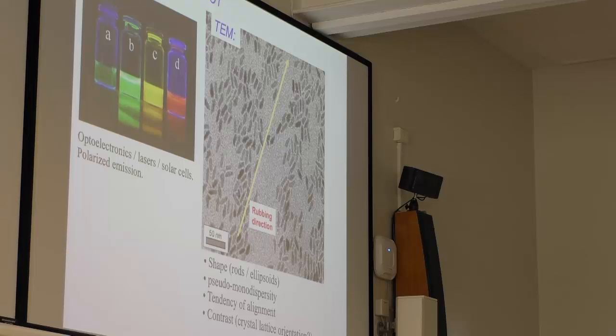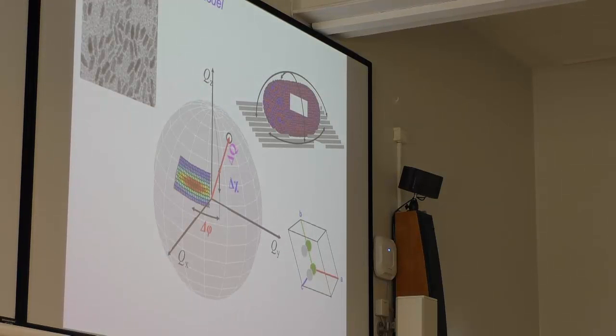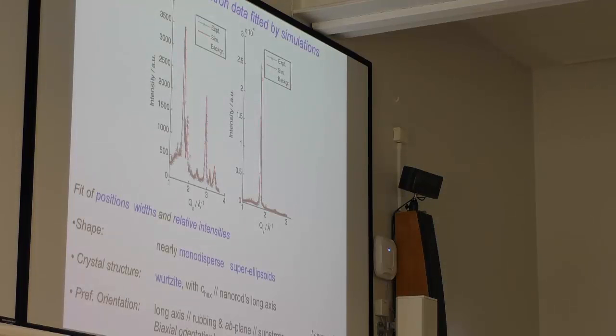Yeah, so we developed this parameterized structural model to deal with these different aspects in terms of orientations and shape of these particles, and we're indeed able to model this quite closely. So, yeah, the crystal structure turned out to be Wurtzite, and as one could guess already from the TEM images, the long axis tended to be parallel to the rubbing direction, and the AB plane of the crystal structure was parallel to the substrate. So they were biaxially oriented, these particles.